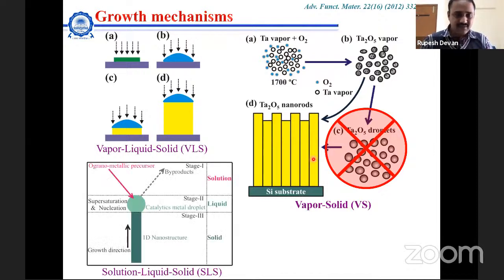And there is another method where you can go with a closed reaction, which is called the solution-liquid-solid growth mechanism, where you can have organometallic precursors with catalytic particles. So this organometallic precursor will reach the supersaturation state after nucleation, and then that will let the solid growth happen. And during this supersaturation state, byproduct will come out. But this byproduct will always remain inside this closed compact reaction chamber. So it may happen that these byproducts can get intercalated with this structure. So if you want pure structures, pure materials, then you can go with the vapor-solid growth mechanism.